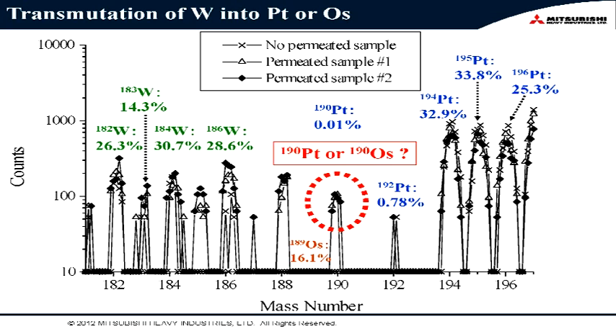But platinum is here, and mass number 190 platinum should be 0.01%. So we cannot see it at mass number 190. Also, we cannot see mass number 189 for osmium, so we can see that we have no osmium in this sample. So this increase at mass number 190 might be attributed to the generation of platinum 190 or osmium 190. But it is necessary to confirm these results by other experiments, for example XRF or XPS, other elemental analysis. It's our next work, I think.